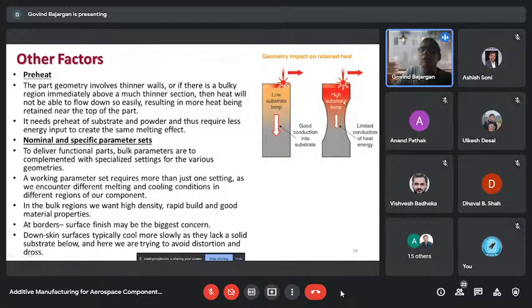So we have to find a solution from part to part. Generally, the solution for this kind of problem lies in heating the bed to reduce the thermal gradient. There are many other things like overhangs. The bottom portion of overhangs is supported by powder, and powder will not have that good thermal conductivity. So the cooling rate will be slower there, there will be some change in the microstructure, and some change in properties may be expected. So these things we have to tweak with the parameters.